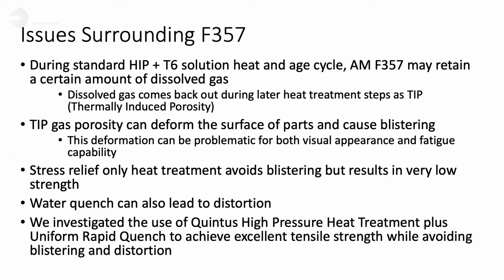F357, when processed in additive manufacturing, also tends to absorb dissolved gas, probably hydrogen from water vapor exposures, either as the powder or during heat treatment processes. And after a high temperature, high pressure heat treatment like hot isostatic pressing, the dissolved gases can come out in later processes when that pressure is released. So you can have a part that looks good after a HIP process that then forms what we call blisters on the surface of the parts during the subsequent solution heat treatment or aging processes.